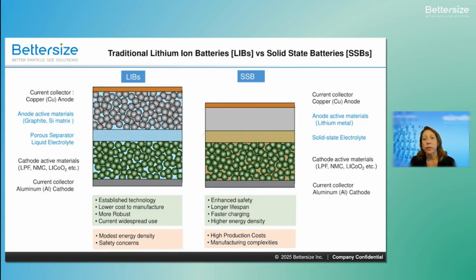The biggest difference with these electrolyte and electrode materials is in the interface characteristics. Because we are going from solid-liquid contact to solid-solid contact, this results in smaller contact area, and we have higher interface resistance. So while SSBs have a negative cost difference, the gains are energy density, charging speed, and thermal stability.